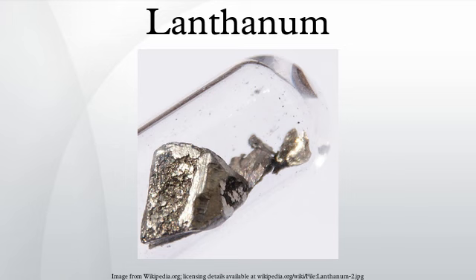Production. Lanthanum is most commonly obtained from monazite and bastnäsite. The mineral mixtures are crushed and ground. Monazite, because of its magnetic properties, can be separated by repeated electromagnetic separation. After separation, it is treated with hot concentrated sulfuric acid to produce water-soluble sulfates of rare earths. The acidic filtrates are partially neutralized with sodium hydroxide to pH 3 to 4. Thorium precipitates out of solution as hydroxide and is removed. After that, the solution is treated with ammonium oxalate to convert rare earths to their insoluble oxalates. The oxalates are converted to oxides by annealing.